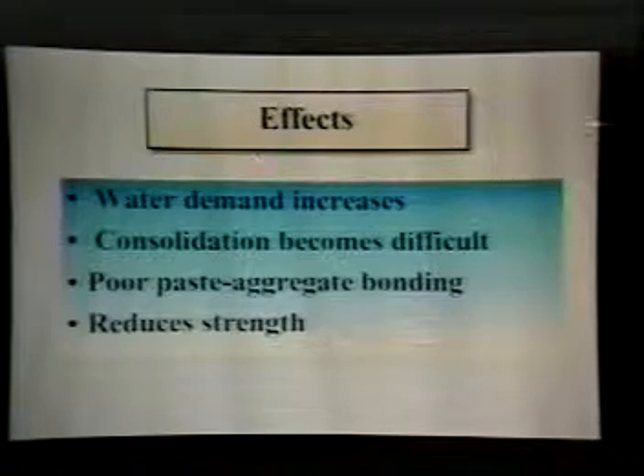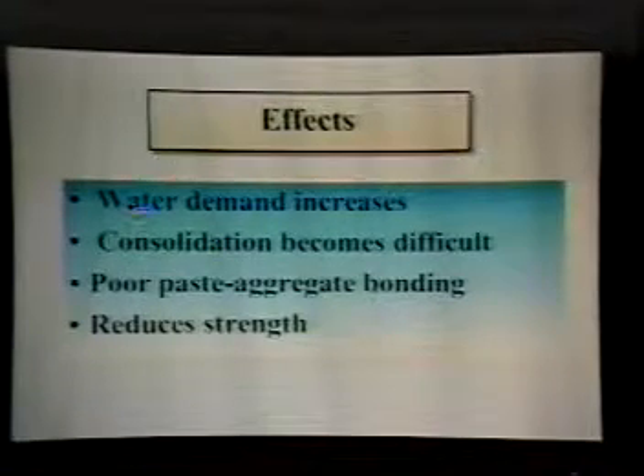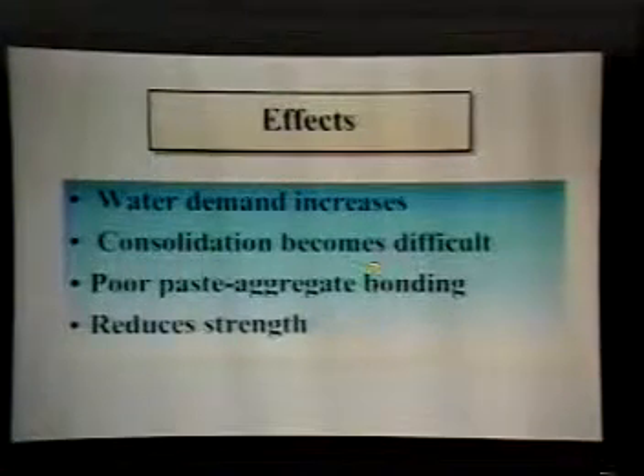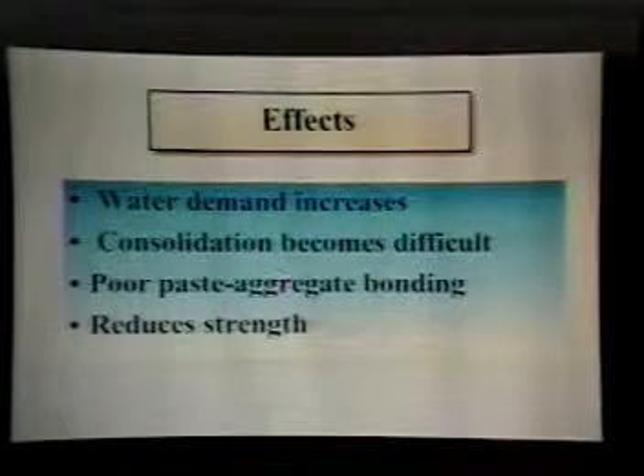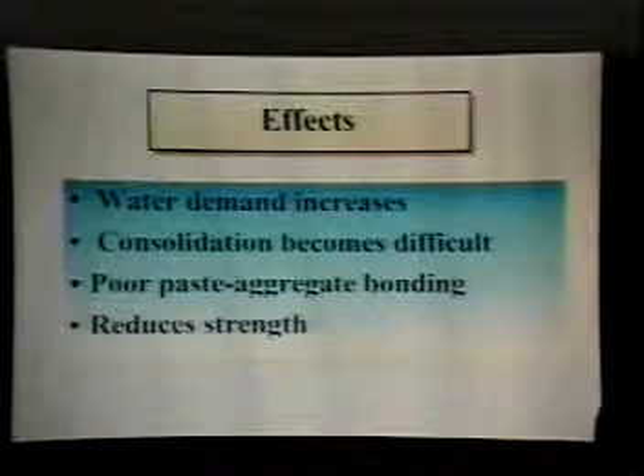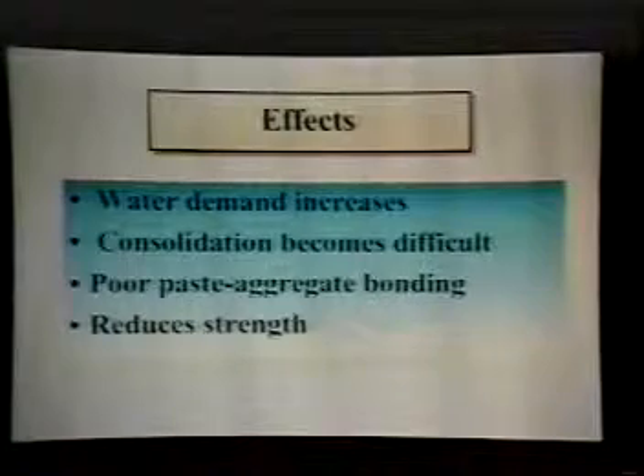Reactive aggregates, strained quartz. This is the extinction of the quartz. If you move the polarizer a little bit, I don't want to go into details, you will see that you have a very short extinction. This is what we call reactive or strained quartz and can cause alkali aggregate reaction in concrete. What are the effects of using improper aggregates? The water demand increases, consolidation becomes difficult, you have poor paste aggregate bonding, and eventually it reduces the strength in concrete.